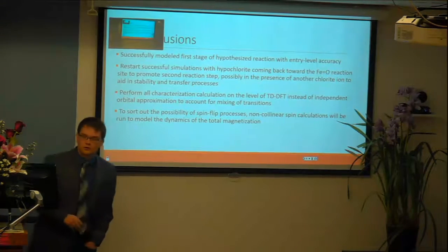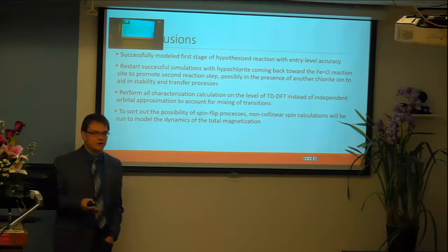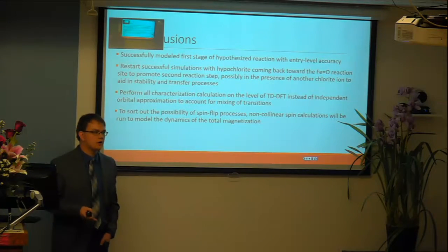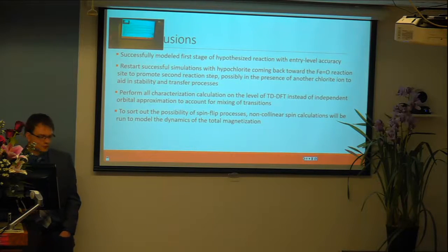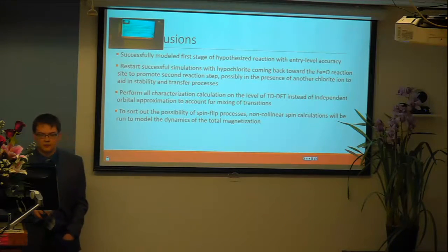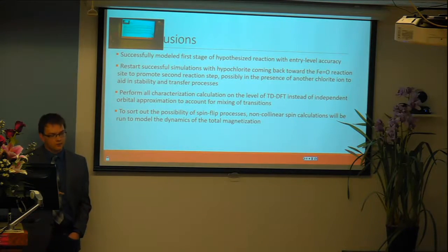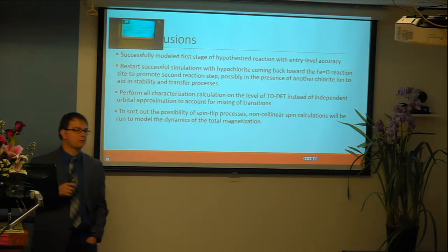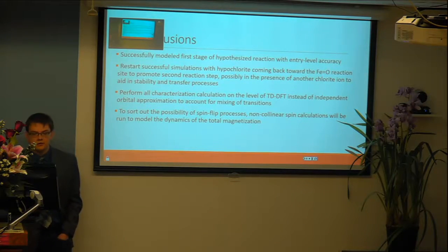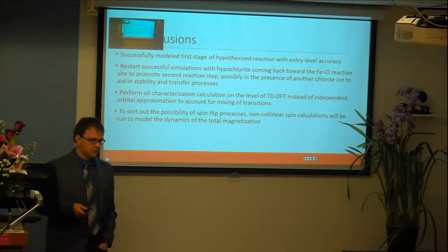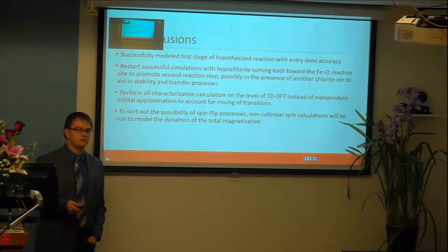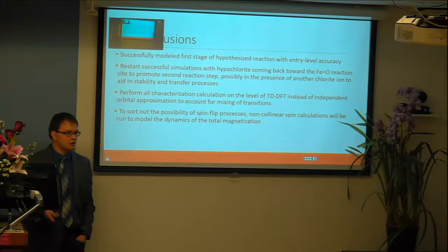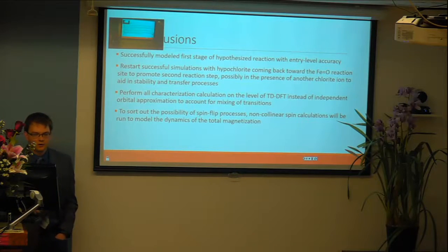So conclusions: we successfully modeled the first stage, not quantitatively, but very qualitatively. And so now we can restart simulations with hypochlorite coming back in, say from another direction, to try and form that peroxy bond that we're interested to see. And we can do all this at a higher level if we would like, but qualitatively it seems to agree with what we think, except for the total energies in anionic systems by themselves.